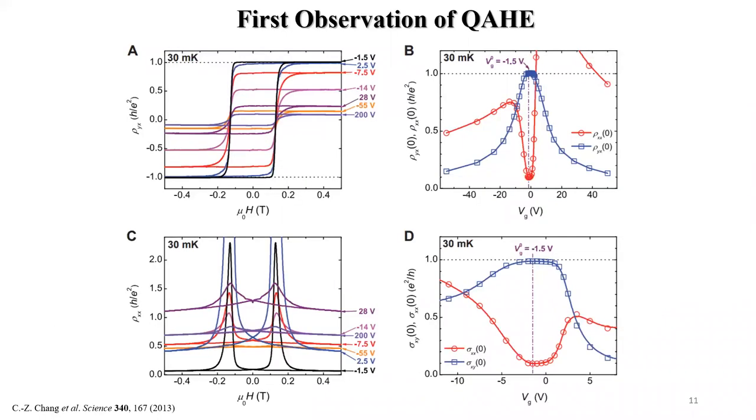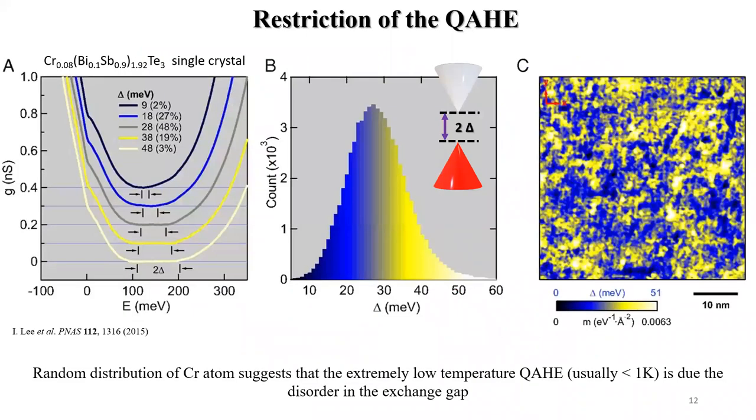The next question we want to ask is why the working temperature for the quantum anomalous Hall effect is so low. It's about 30 millikelvin. It's pretty low, and hard for daily life applications. There's a research paper that mentioned this. As you can see from this STM spectra, the scanning tunneling microscope is very sensitive to the surface gap. They found that